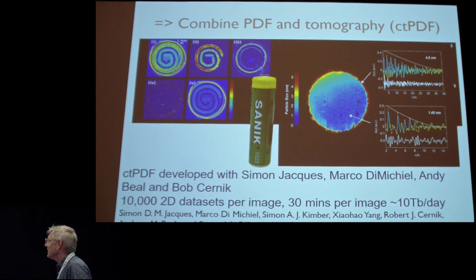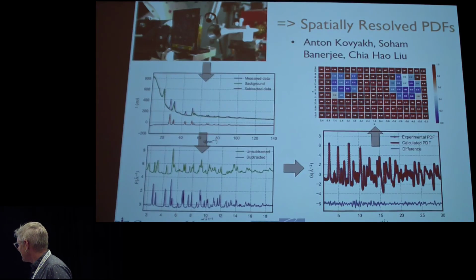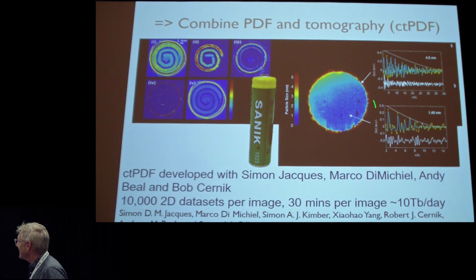And then what we did recently was take this one step further and combine it with computed tomography. So what we can do is take a 3D object. In this case, it's a catalyst body with palladium nanoparticles on it. And we take 100 data sets as a function of position across here. Then we rotate it 2 degrees, we take 100 more, 2 degrees, 100 more. So we have 100 by 100, 10,000 data sets. And each of those data sets is a sum of all of the scattering through that region of the sample. But you apply the tomography and it produces 10,000 pixels. And inside each pixel we have a complete PDF, which we can then model.